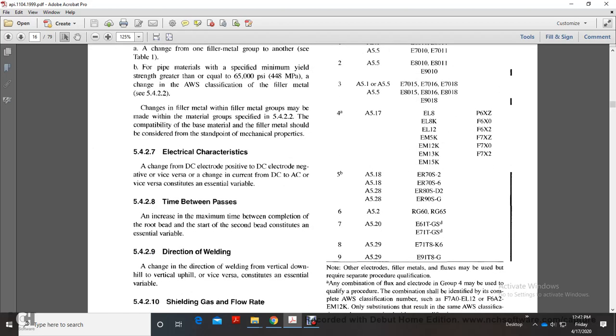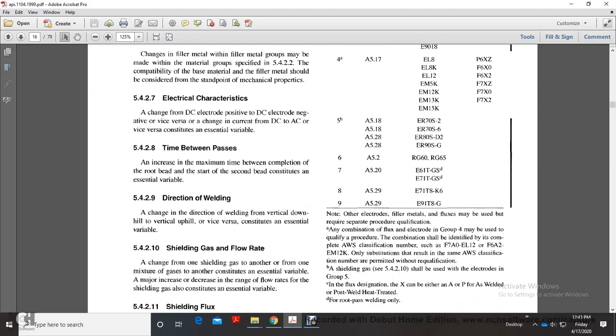5.4.2.7 Electrical characteristics. A change from DC electrode positive to negative or vice versa, or a change in the current from DC to AC or vice versa, constitutes an essential variable. 5.4.2.8 Time between passes. An increase in the minimum time between completion of the root bead and the start of the second bead constitutes an essential variable. 5.4.2.9 Direction of weld. A change in the direction of the weld, vertical downward or vertical uphill, or vice versa, constitutes an essential variable.